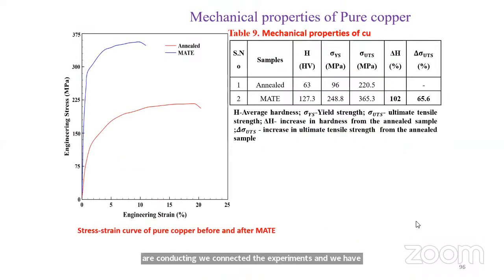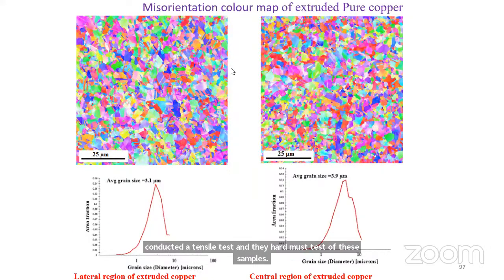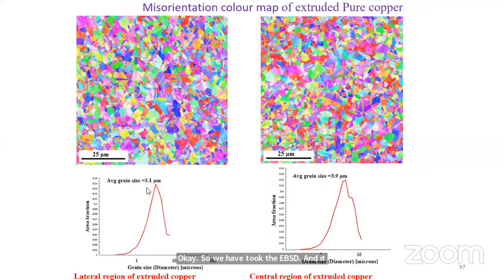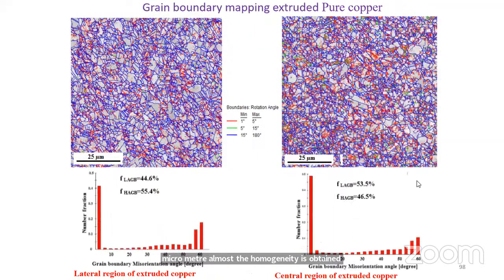We took the EBSD results of these samples. We can attain an average grain size of 3.1 micrometers. In the lateral region and the central region, we can obtain 3.9 micrometers. Almost homogeneity is obtained in the average grain size on both sides. This is the lateral region of the extruded copper. The percentage of low angle grain boundaries is 44.6%, whereas high angle grain boundaries is 55.4%.